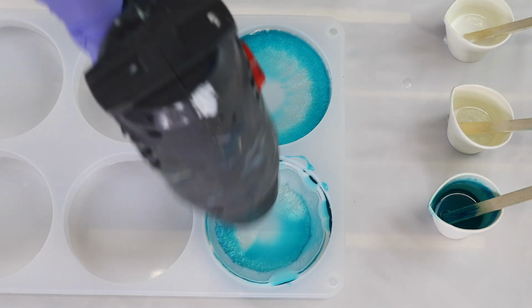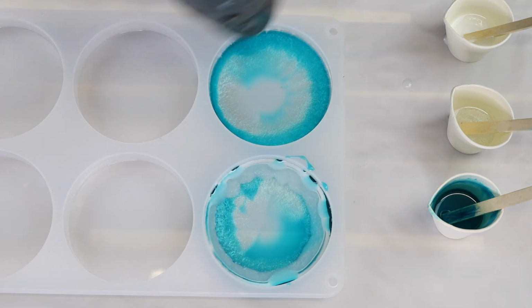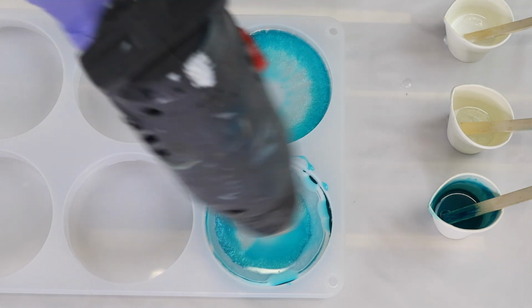And along the lines of heat, heat pops bubbles really well in resin, but it can only penetrate down so deep. So if you do have a good amount of resin that you have mixed up and you use your heat gun, it's only going to get the surface where those bubbles are. It will not penetrate the whole way down. And that is an issue that a lot of people have when they do casting items, because we are pouring into molds and they are going down lengthwise and not out like you would with an art resin because you're pouring over a surface, is getting those bubbles out using heat.